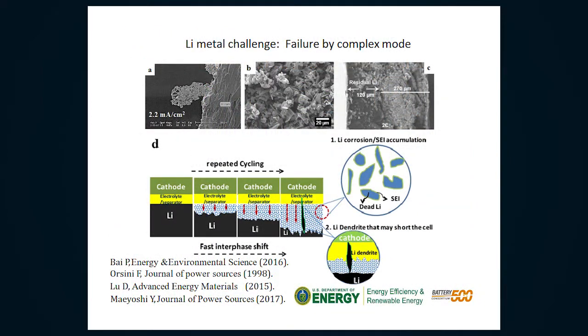And then the most difficult problem is the lithium metal. Though we know people are worried about lithium metal dendrites, everybody who has done anything on batteries knows dendrite is a big problem for lithium metal. But what I want to say is, under the real cell conditions, in our system, way before we see any dendrite formation, the cell already broke. We are using a very small amount of lithium metal, high cathode loading, and a very small amount of electrolyte. In this case, the whole lithium electrode architecture degrades very, very quickly. The whole lithium metal can become an SEI layer. So that's really very bad.